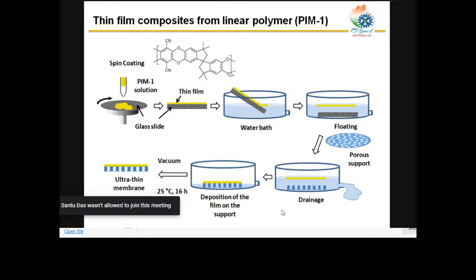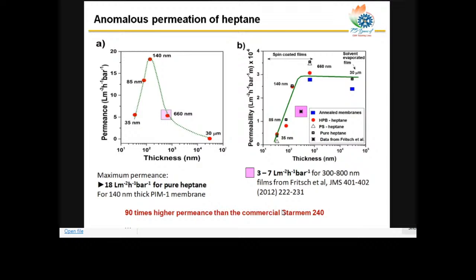So what do you observe here? This thin film, next please. If you see the left side of this graph, we are plotting permeance against the thickness of the membrane. With decreasing thickness, we are getting increased flux, or higher permeance. With a thickness of about 140 nanometers, we are getting the highest flux.